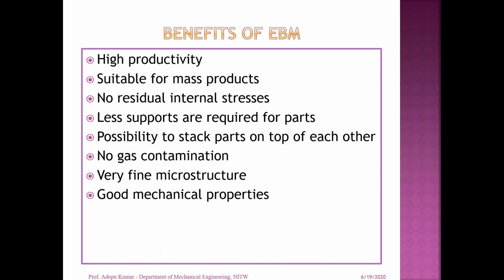So the benefits: you can have high productivity, because you can use an electron beam with high power density compared to a laser as a power source. That's suitable for mass production, and no residual or internal stresses develop, because you can concentrate on only a particular area, and other areas are not affected that much as in the case of the powder bed fusion process. So fewer supports are required for parts, and it is possible to stack parts on top of each other. There is no gas contamination, and very fine structure and good mechanical properties, because you are using a vacuum as the environment in the electron beam melting process.